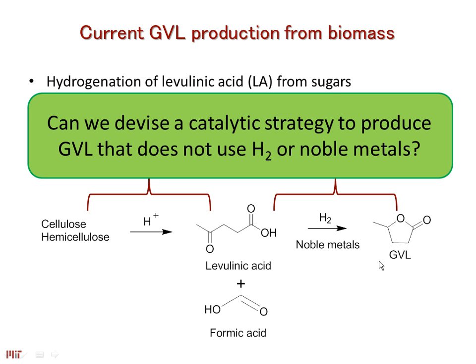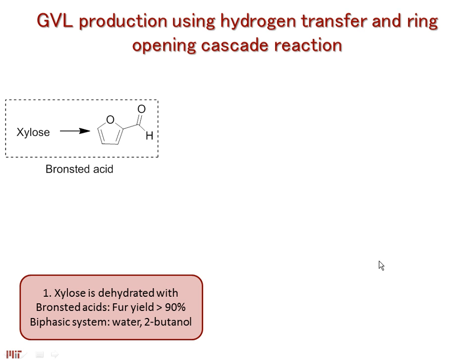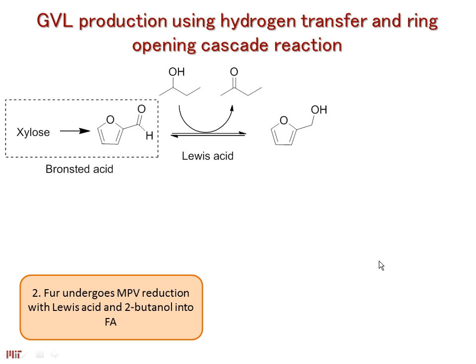So what we wanted to ask is, is there a way for us to produce GVL, perhaps without the use of molecular hydrogen or precious metals? And as you can imagine, what we want to exploit then is the ability of these Lewis acids to do transfer hydrogenation chemistry. So imagine a process where we start from xylose to produce furfural. There's a lot of well-established methods on producing furfural in high yields from xylose. And you usually use a Bronsted acid catalyst for this step. You can perform then a Lewis acid transfer hydrogenation step where you convert your furfural into furfural alcohol using a sacrificial donor, and we will talk about what we do with this product in a little bit. But you perform transfer hydrogenation chemistry where you transform your furfural into furfural alcohol.